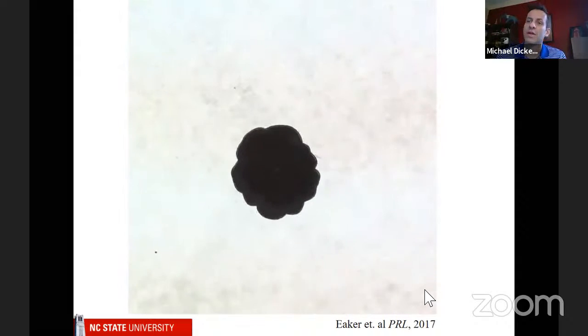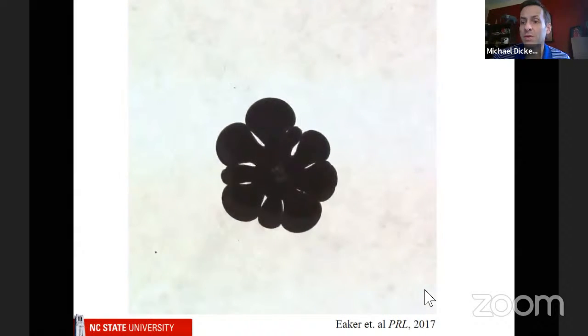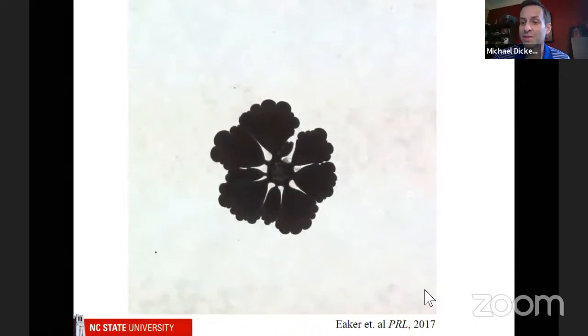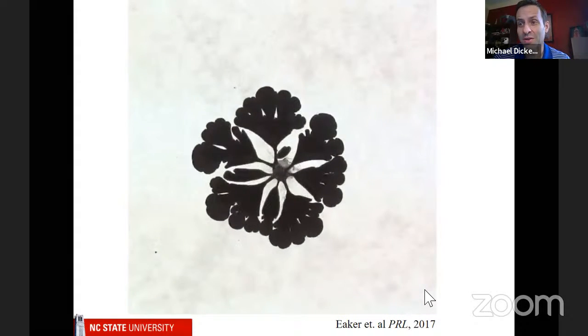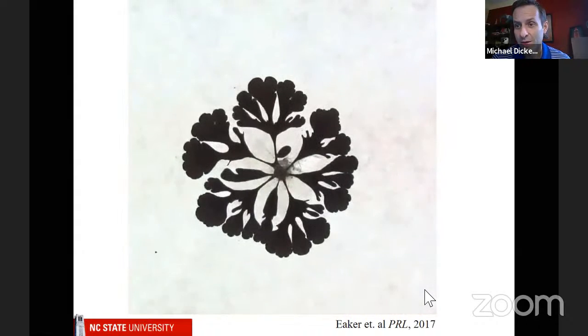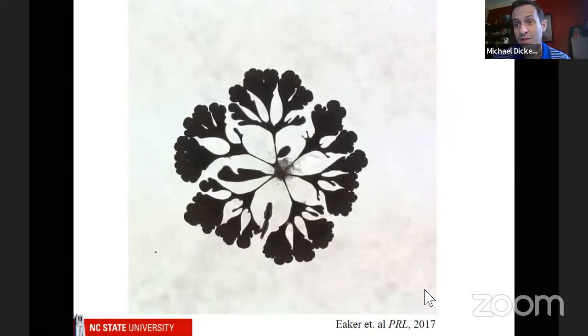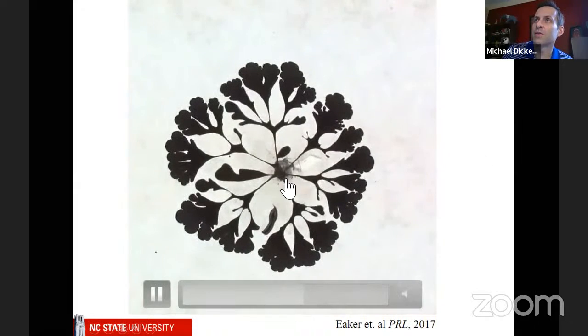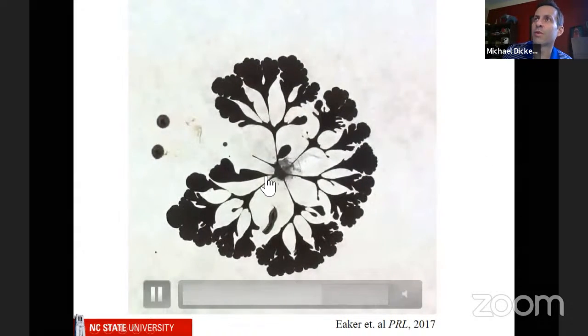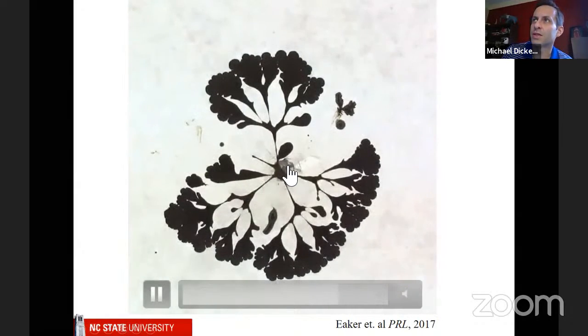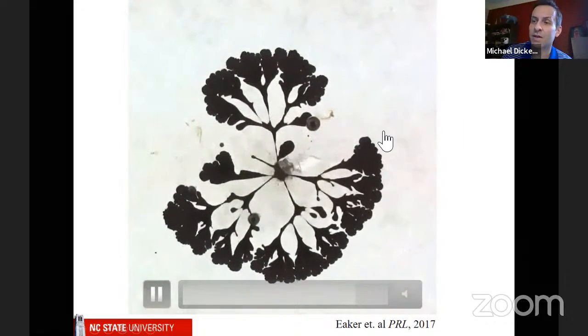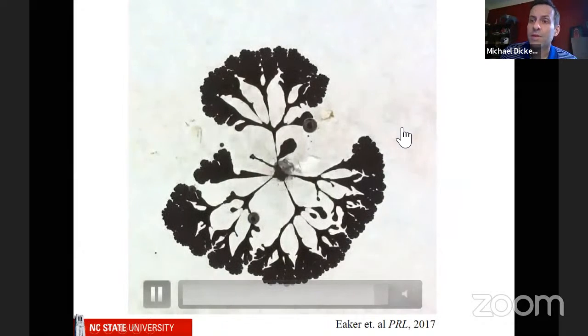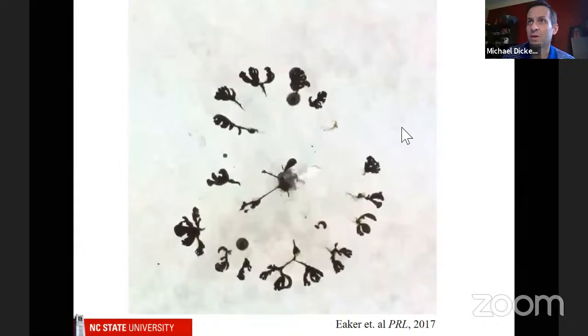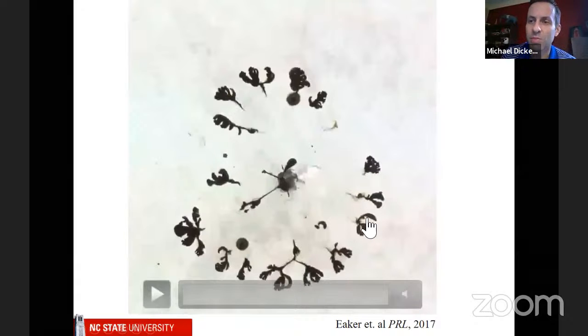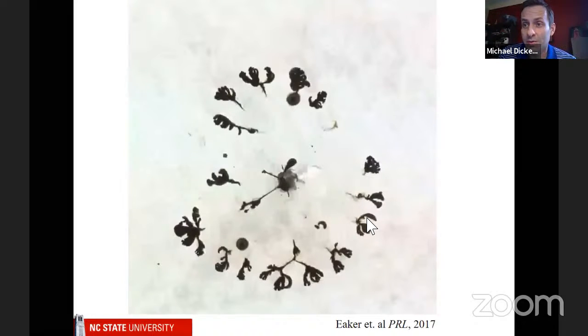So here's the liquid metal. We apply that voltage, and the metal starts to spread. Not only does it spread, but it actually starts forming fractals. Now, this is really weird, because we're only applying 1 volt, or a little bit less than 1 volt. Now, you'll see at some point that some of these little things will break, like that one breaks. Remember, the electrode is right here. So as soon as it breaks, it's not connected to the electrode anymore, and the oxide dissolves off and it just beads up. So clearly this is driven by this electric field. And then when you turn the voltage off, it just all beads up.